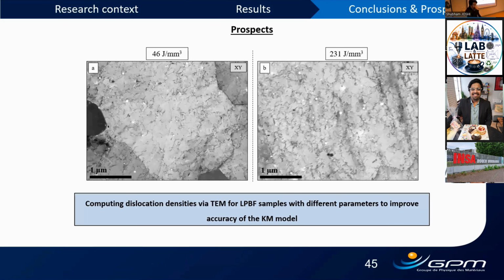Another prospect which I would like to discuss is when we compare different volumetric energy densities and look at the contribution of microstructure to yield stress, we made a very strong assumption that the dislocation density in soft zones should be equal in all the samples. The magnitude should be similar, in order of magnitude, and this is what we get from the literature, but certainly it's not the same. So as a prospect, I would like any person who is interested in taking this research further to compute dislocation densities extensively by TEM to increase the accuracy of the model.